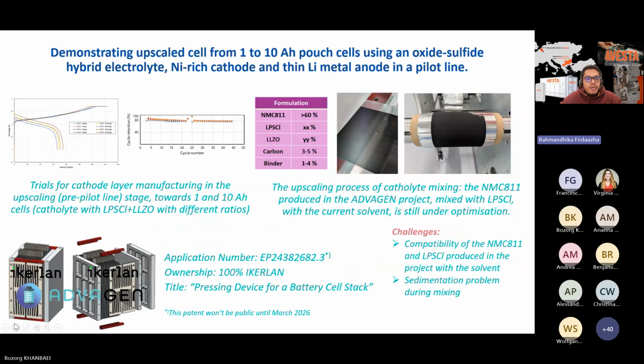After we see that we have stable performance for the pre-pilot line, we try the upscaling process. Going from lab activity to intermediate activity to the upscaling process has its own challenges, because a small batch of mixing and making slurry will be different from a bigger batch. In the upscaling of catholyte mixing, NMC811 produced in the Advagen project, mixed with LPSCL with the current solvent, is still under optimization, because sometimes we have bubbling during the coating. This is a challenge that we can mention.